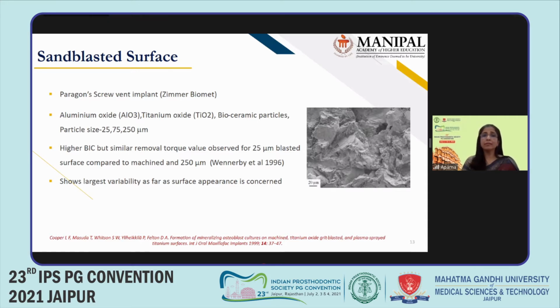Now the reason why the surface is anisotropic is because when you start off the blasting cycle, that is the first cycle, you have the sand particles with a certain size. Once it is blasted, because of the impact, the gritting particles tend to break. So when it goes through the second blasting cycle, the size of the sand that is hitting the implant shank is much smaller, and so on and so forth. So every time you're subjecting the implant to a blasting cycle, the size of the particle used for blasting reduces, and because of which you have a very irregular and anisotropic surface. Is that clear?